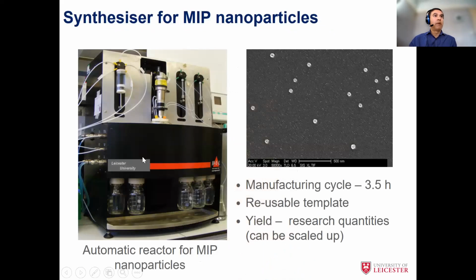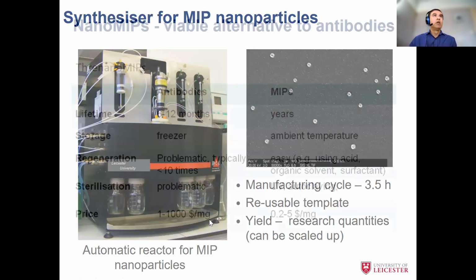And we've developed and made an automated machine that can actually synthesize batches of nanoparticles with very little deterioration in performance and also the size and shape. This is an SEM showing you that the size and the shape are quite uniform. So the cycle is about 3.5 hours. You put your reagents in and you end up with a pot of nanoparticles at the end. The beauty is that the template that is immobilized on the surface of the glass bead can be reused. So if it's a virus or a protein or a peptide that is very expensive, you can regenerate the column and then make significantly more nanomaterials. And you can make research quantities and they can also be scaled up. And this is what some of our BSc project students and our MChem project students and obviously our PhD students have been working on. So why?